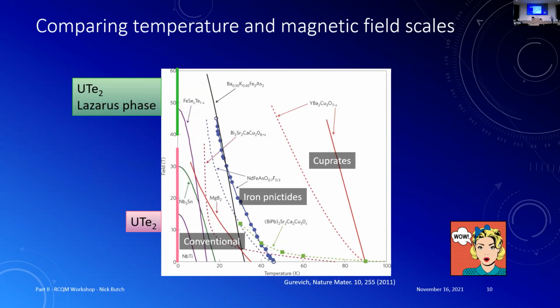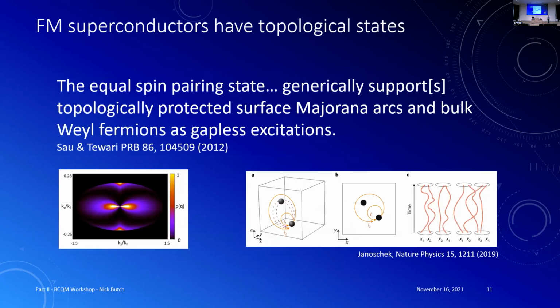But if you don't care about that stuff and you just want to be spoon-fed a line, I want you to just compare the temperature scales and the field scales of UTe2 to basically everything else we know about. So having a 45 Tesla upper critical field, not such a big deal if you're a cuprate, right? But your TC is huge. Here on this plot, this is a delta function, right? TC is two, but a little bit below two. And so this is actually quite remarkable. Even if you ignore topology, if you ignore everything, this is a weird material.